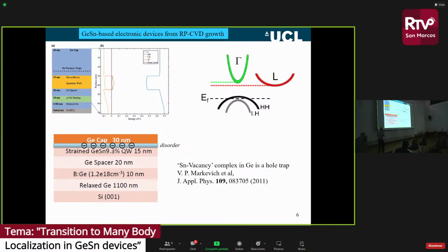Okay. What we find in our devices is that they are p-type, so the chemical potential is down in the valence band. So this is what the structure looks like. It's a kind of a redrawing of this structure. And what happens in this system is we've got this tin quantum well here, and the tin is such a large atom that it tends to surface segregate. So it tends to surface segregate towards the surface as it's growing and forms a disordered layer. The tin forms a complex with a vacancy, which is a hole trap. So we can trap holes here at this interface. So that's where we get this disorder from.